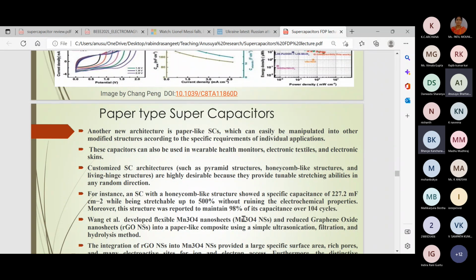So this structure was reported to maintain 98% of its capacitance over 104 cycles. So now we've come down for paper type capacitors and these sort of applications. We do not have that kind of cycle life yet. No 500,000 cycles. It's just 104 cycles or so. So there are always pros and cons to everything.